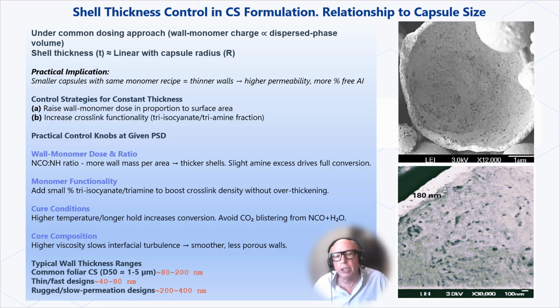For foliar applications, we are typically looking at 80 to 200 nanometers. Thin, fast designs might run 40 to 80 nanometers, while rugged, slow permeation designs can go 200-400 nanometers.